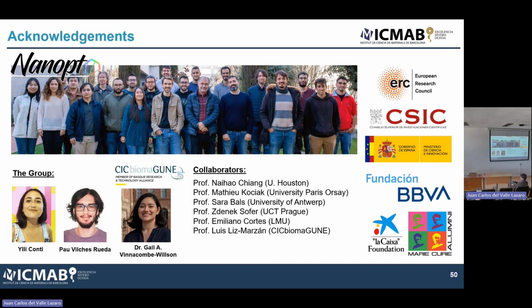So basically, you start importing all the knowledge that you have from the colloidal system to the in situ one. The problem that we are facing in situ is the characterization, because of course we cannot use TEM, so that is complicated. It's much harder to monitor this type of evolution and stability, but we're working on it, coming up with a few ideas to try to understand the system better overall. But the problem is always oxidation for us, because at the nanoscale they tend to oxidize very quickly, especially if you're talking about silver.